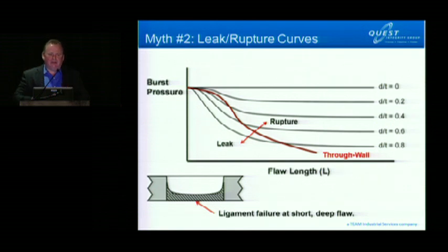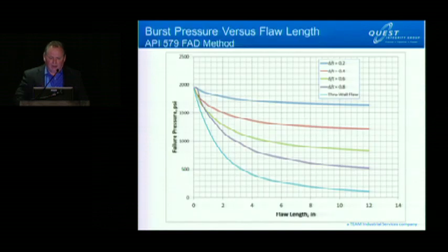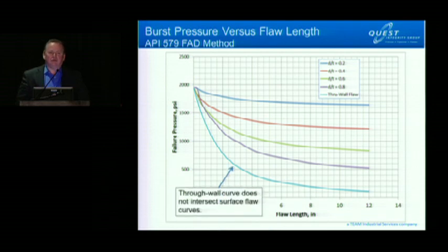The problem is that this doesn't actually happen when you look at a modern fracture mechanics model. Here's what API 579 predicts. These are burst pressure versus flaw length for different depths, and the bottom light blue curve is through wall. And notice that the through wall curve doesn't intersect the other ones. I thought, well, is that just a problem with the math of the API 579 method? So I ran some finite element simulations. I compared an 80% crack to a through wall crack at various lengths, and I found that from the elastic plastic FEA, the through wall crack was always worse in terms of crack driving force than the 80% flaw. So that's myth number 2.